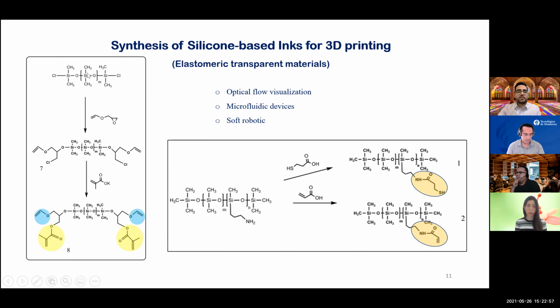For that reason, we can use the same logic I already mentioned in the previous slide, based on different functional groups in between, and it's based on silicone chains, silicone oligomers, or maybe silicone prepolymer. We can use the same strategy, adding some groups on the surface, such as vinyl and methacrylate groups, and at the same time functionalize other kinds of silicone oligomers. Mixing those, we will have the final structure for the inks, for the resin for 3D printing. We already purchased all materials, and I hope we can start synthesizing those materials maybe in 1 month.